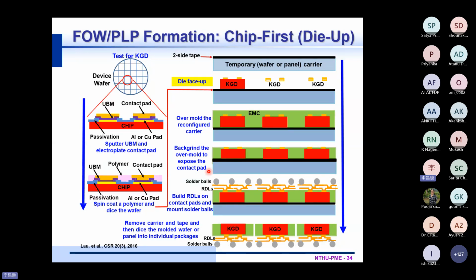Because if we just use the metal ring to directly restrain the warpage, maybe there will be some cracks during the process. So this needs to be analyzed, okay? And after the back-grinding, then the RDL structure, ball formation, and the dicing. Okay.